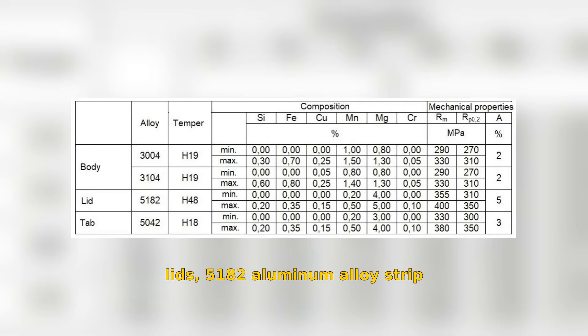For lids, 5182 aluminum alloy strip in H48 temper is used. For tabs, a strip of 5042 aluminum alloy in H18 temper is used.